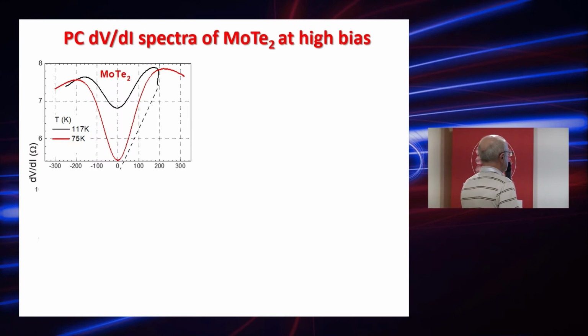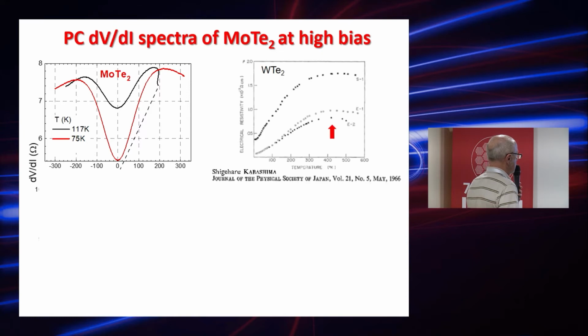So here is shown differential resistance of point contact between silver paint and molybdenum ditelluride. We see that this characteristic shows metallic behavior, that is, differential resistance increases with voltage, and then at higher voltage we observe such a decrease in differential resistance, as I showed before, similar to the decrease of the resistivity in tungsten ditelluride. So such a change of differential resistance behavior from metallic to semiconducting.